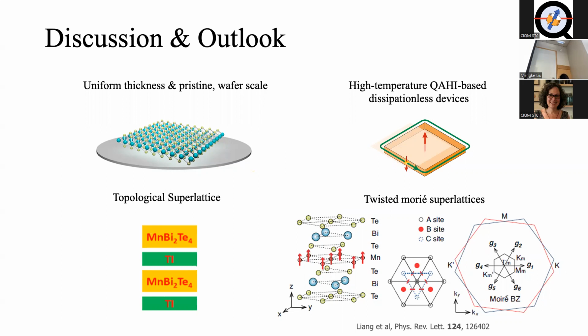So if we translate by half unit cell, because the stacking is different, here if we translate by one septuple layer, it becomes this, which is down. So these two are the same. So it breaks time reversal symmetry for sure, and it opens up the gap. That's right. And people argue that the even septuple layers can be axion insulators. I don't want to comment too much about axion insulators because I don't know if I'm qualified for that. But it's also a topological phase, and it opens up a gap at the surface. Both top and bottom surfaces will have a gap. Yeah, no problem.